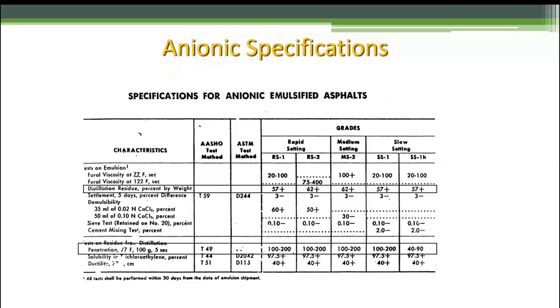Tack coat is the oil we put down to bind two layers, chemically weld two layers of asphalt, two lifts of asphalt together. So the important thing in here is distillation residue. Well, what does that mean? Percent by weight here. By weight, not by volume, as we looked at in cutbacks, by weight. Well, the residue is the asphalt. So in that gallon of emulsion, we weigh that out, at least 57% of it has to be residual asphalt for an RS1.